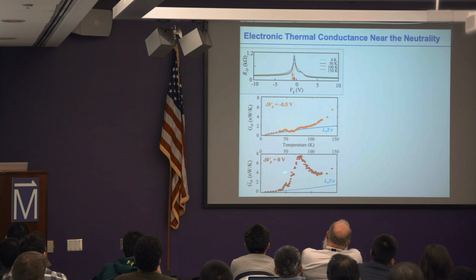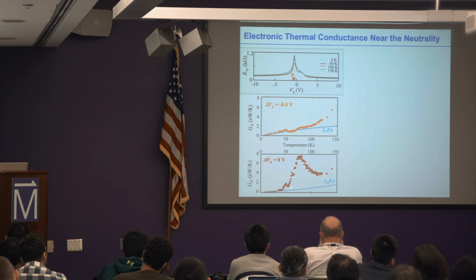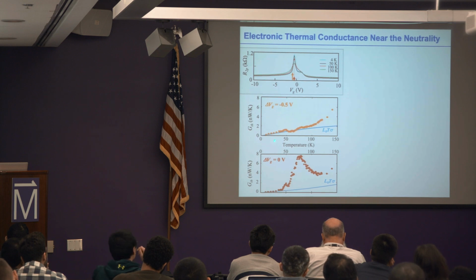Right at the Dirac point, at low enough temperature, I still have the data following the Wiedemann-Franz law, but it starts to really deviate around 30 or 40 Kelvin. It picks up, starts to decrease, and increases again.